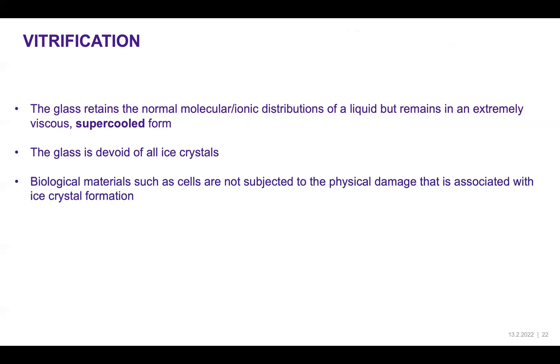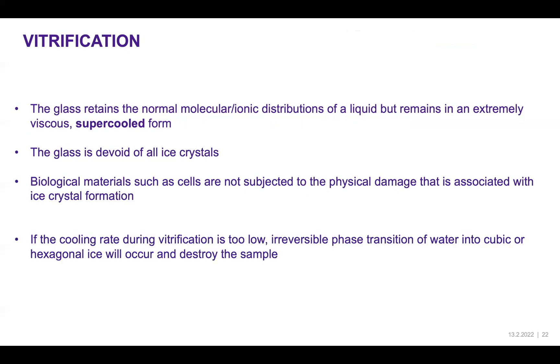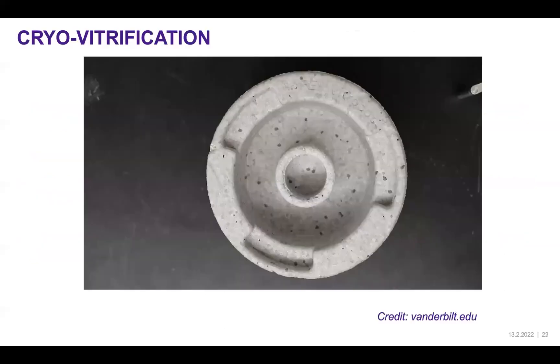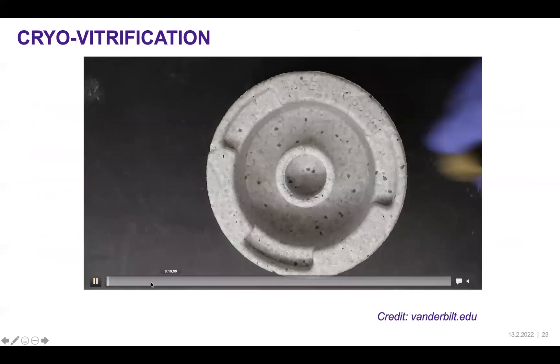Since this glassy state has no crystals, biological materials are least affected. If water inside a cell crystallizes, it breaks and deforms the cells — so this is a great advantage for particles sensitive to crystallization. It is therefore important not to cool your TEM grid slowly, because slow cooling produces ice leading to irreversible phase transitions that destroy your particles.